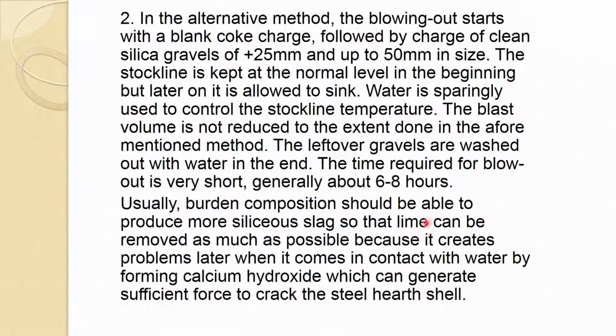In the second one, the alternative method, the blowing out starts with a blank coke charge followed by a charge of clean silica gravel of 25 millimeter up to 50 millimeter in size. So, it starts with this material from the starting. The stock line is kept at the normal level in the beginning, but later on it is allowed to sink. Water is sparingly used to control the stock line temperature.